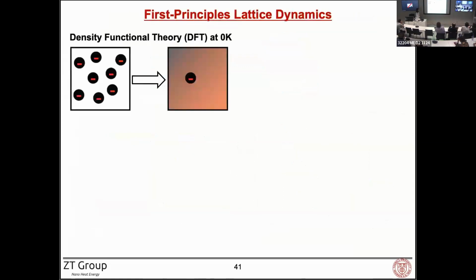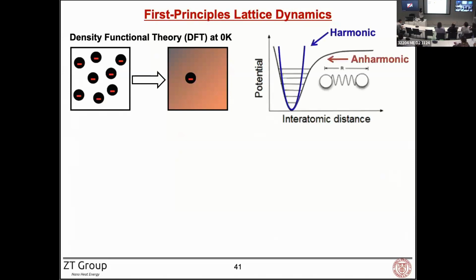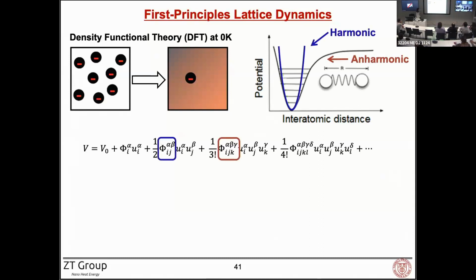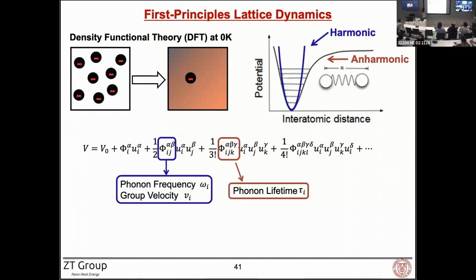Now, I'm going to very briefly introduce the first principles lattice dynamics. We started with density functional theory calculations at 0 Kelvin. Essentially, we are just converting this interacting system to a non-interacting system by looking at the interaction between one electron and the mean field. And that allows us to efficiently calculate the electronic band structure and the forces between atoms. So you look at the interatomic potential, it has a harmonic and anharmonic part corresponding to the second order and the higher order force constants. So the second order force constants give us the phonon frequency and velocity, and the third order would give us the 3 phonon scattering lifetime.